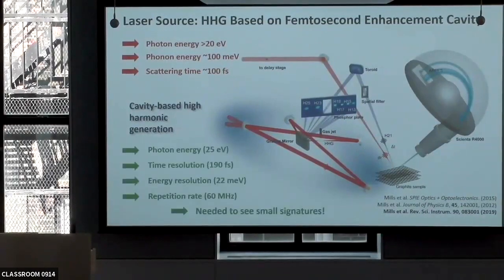So when you look at numbers, photon energy for this particular experiment was 25 eV, but it goes up to 40 eV if you look at the full spectrum. Resolution in time, 190 femtoseconds. In energy, 22 meV. Repetition rate, 60 megahertz. So these are all the parameters you need to do this particular experiment, and a bunch of others. For instance, if you wanted to do Cavaleri's experiment but look at the superconducting gap, we could do it in principle. Or if we wanted to do the same experiment ZX has done on iron selenium, but look at the zone boundary of the gap, we could do it.